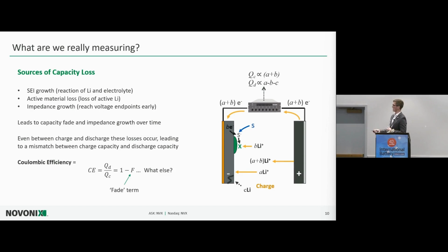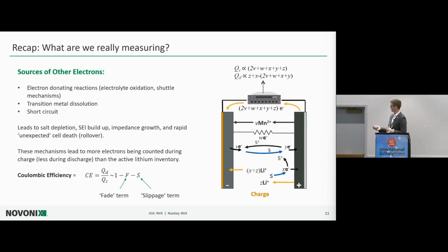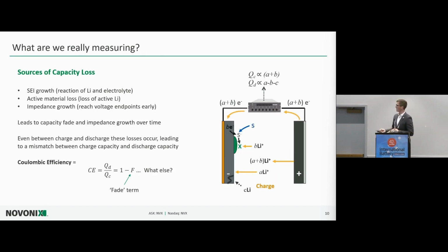As we're charging our cell, we lose some lithium to SEI growth on the anode. We have some particle cracking or electrocracking. We have mass loss happening. So sources of capacity loss can be SEI growth, active material loss. Even impedance growth can then affect how much capacity you are able to obtain each cycle. And this, of course, leads to lost capacity, impedance growth over time.